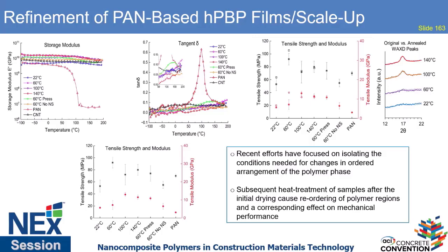And what we've seen here is that we can change the mechanical properties. We're trying to understand it in these films, but when we heat treat these samples with annealing, these X-ray peaks here provide the evidence that the polymer is there. Without annealing, we can't see the polymer crystallize, but it's interacting so well with the nanomaterials because of this blended phase that it basically forms this perfect composite. So this is very exciting for us, and we want to be able to translate this into fibers because we want to make these really nice fibers.